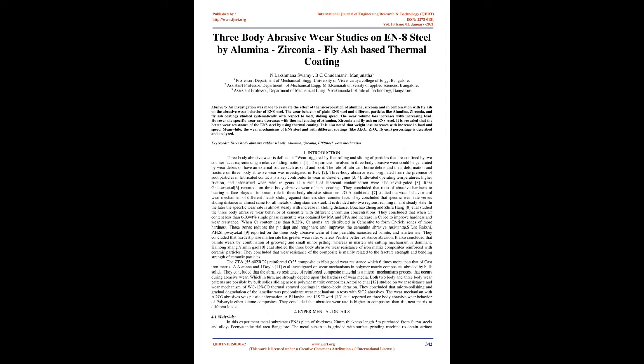The wear behavior of plain EN-8 steel and of different particle coatings like alumina, zirconia, and fly ash was studied systematically with respect to load and sliding speed. The wear volume loss increases with increasing load. However, the specific wear rate decreases with thermal coating of alumina, zirconia, and fly ash on EN-8 steel. It is revealed that the wear resistance of EN-8 steel is better when using thermal coating.